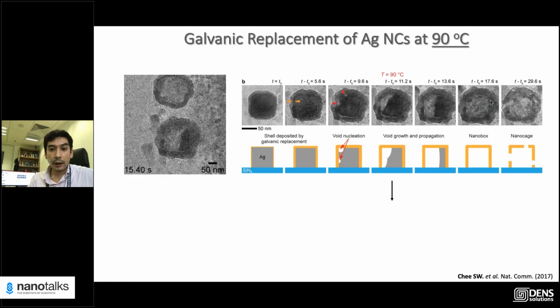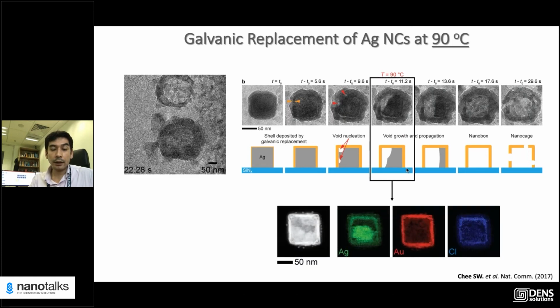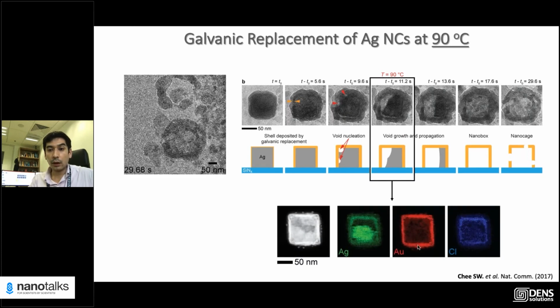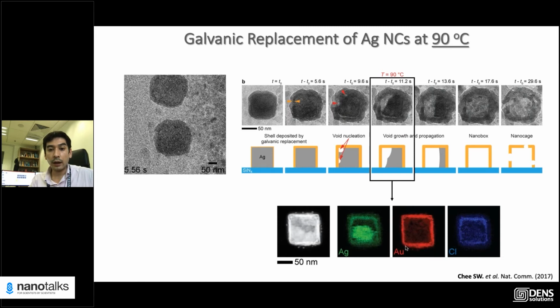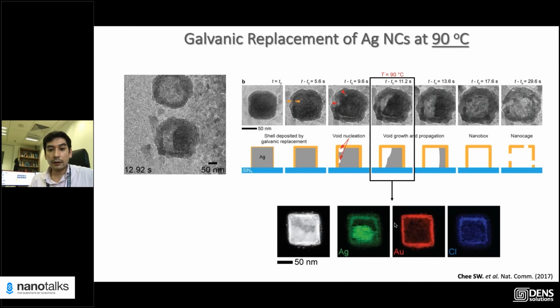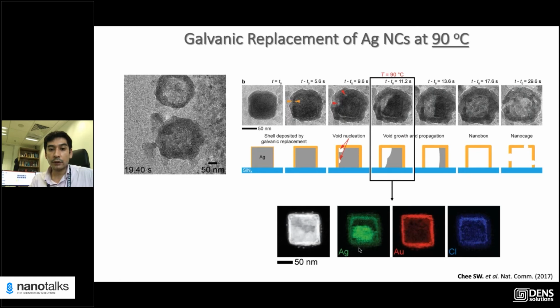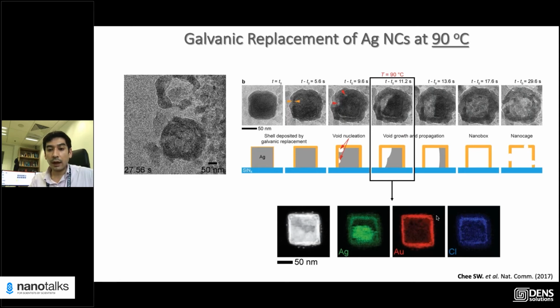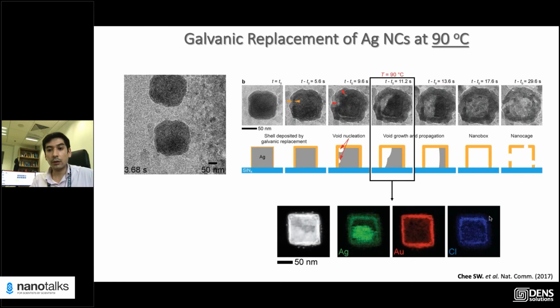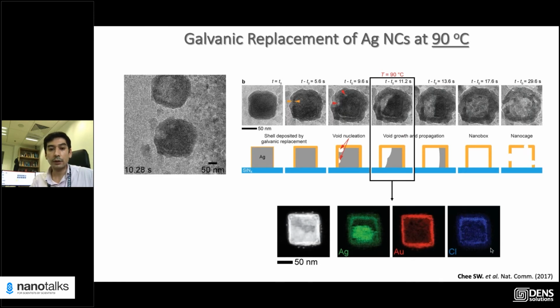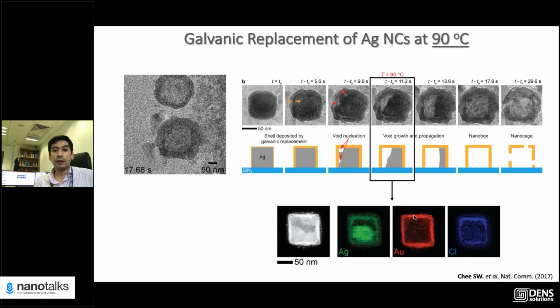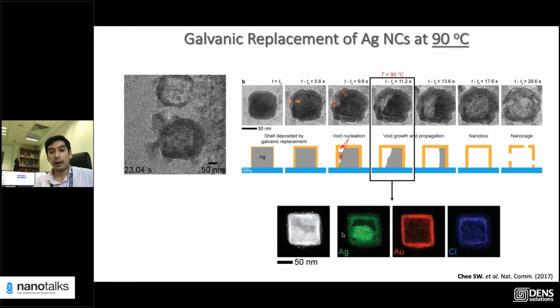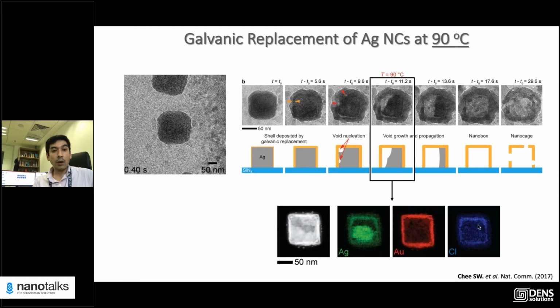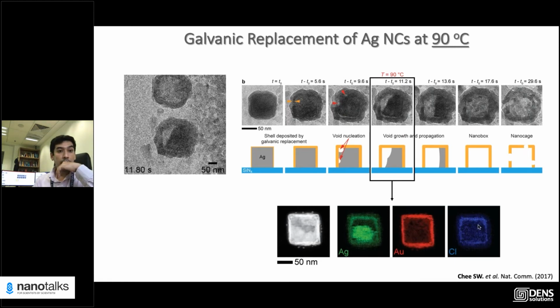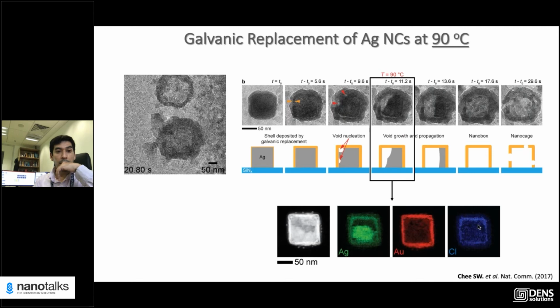And you can actually take the samples and look at them under EDX to make sure that you have gold on the surface, silver is getting etched away, and the surface is a gold-silver alloy forming. And of course, since you have chlorine in the solution, it also deposits on it, right? But essentially, you see this entire reaction happening, and all the elements are more or less in the right place. Okay, so how can we be confident